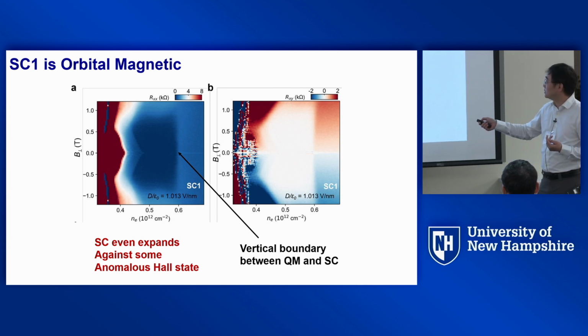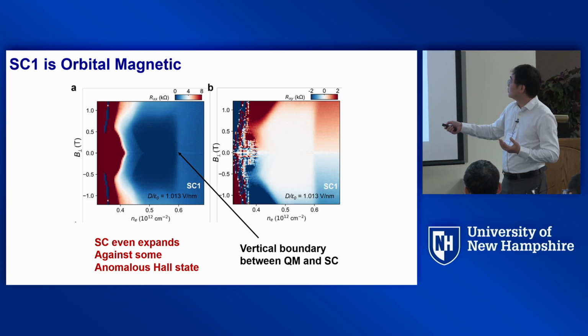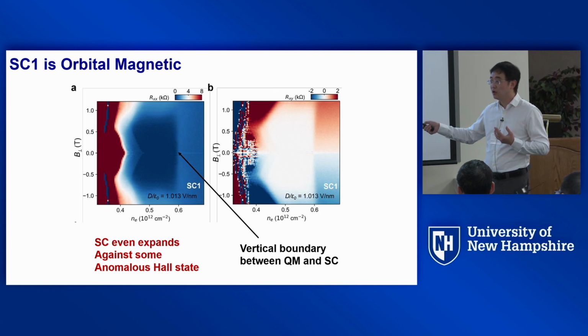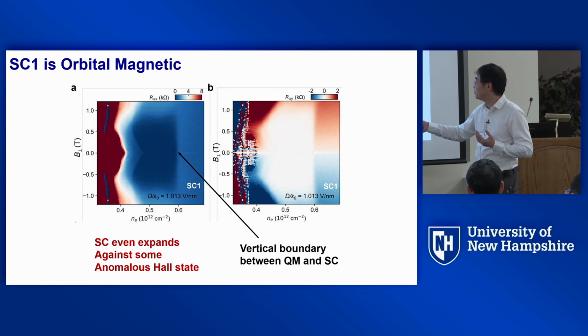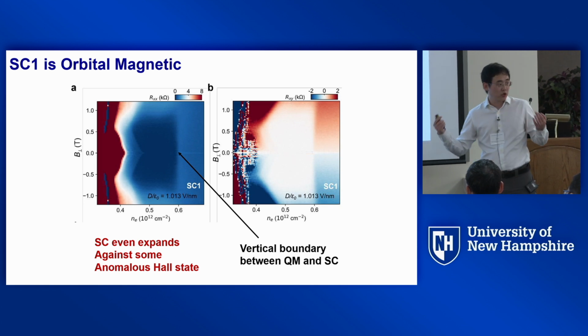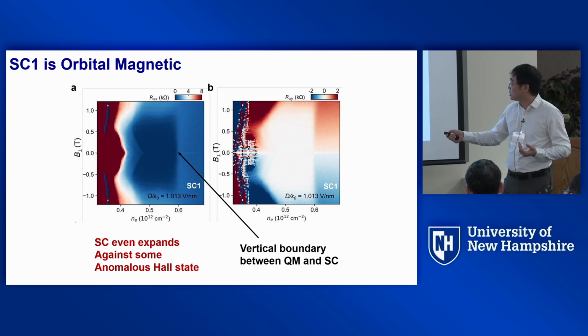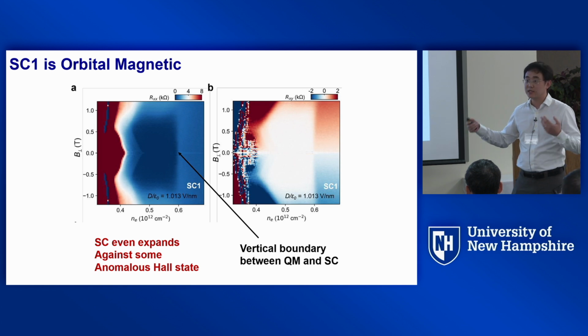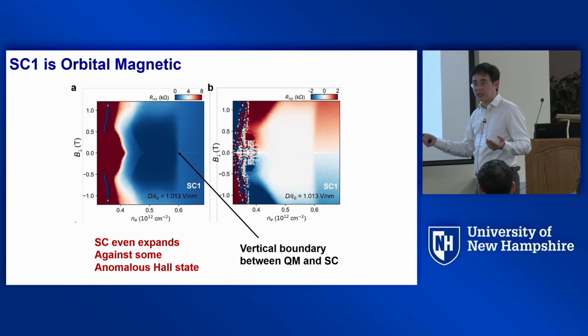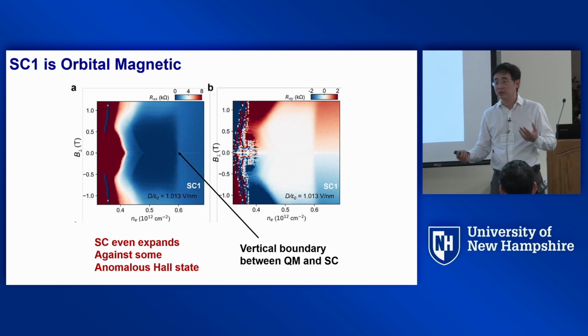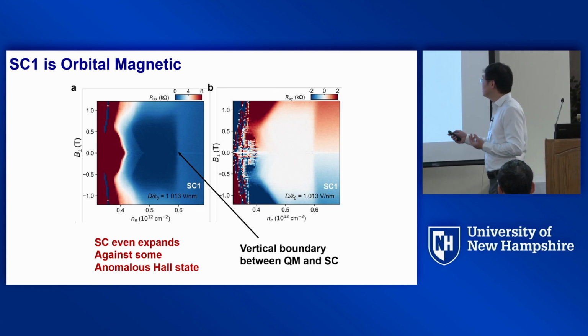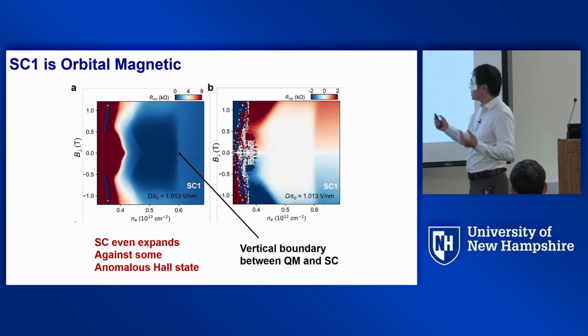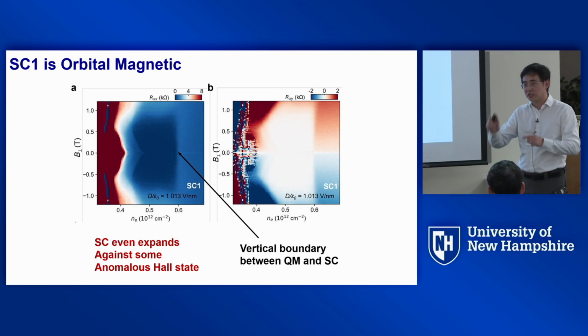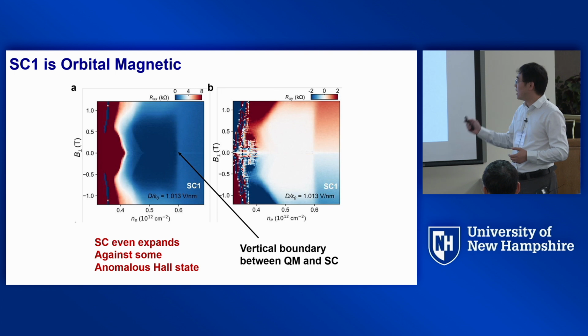And on the left-hand side, the lower density side, it's even more dramatic: the superconductivity, instead of being killed or eaten, actually expands towards lower charge density. Which means if you do a line cut here, if you park at a charge density which does not show superconductivity at zero magnetic field, it will actually become superconducting when you apply some magnetic field. And that also indicates the superconductivity couples to the magnetic field in a way that you expect a magnet does. Okay? But still, this doesn't answer, because we don't have quantum oscillation inside the superconducting region. This doesn't really nail down what is the parent state of that superconductivity.